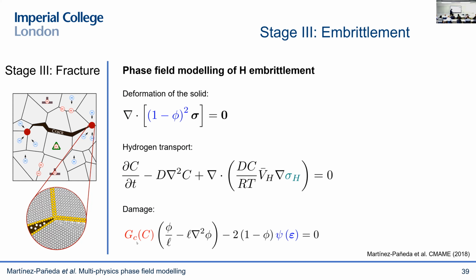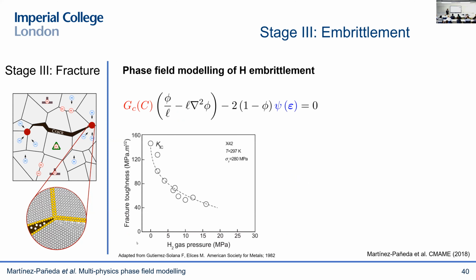So we know, qualitatively, what we need to do, right? We know that what hydrogen does is to reduce the fracture energy in the material, the fracture resistance. So we need to define a hydrogen degradation function. We need to make this fracture energy dependent on the hydrogen content. But the key question is how to do that quantitatively. And there are multiple ways of looking at this. One way is, of course, you can fit it to experiments. And some of our industrial partners do this.